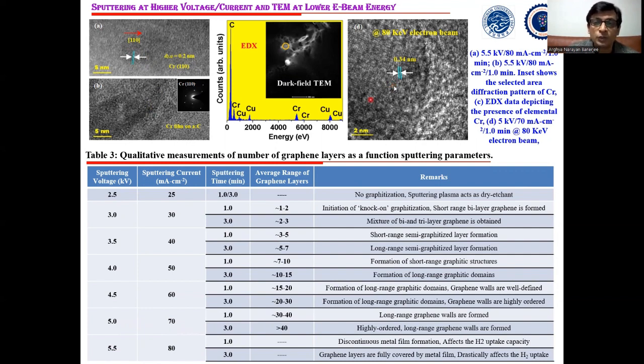And one more thing which we actually corroborated: generally, when we put this amorphous carbon film inside a high resolution TEM system, because a high energy electron beam is irradiated on this amorphous film, this electron beam sometimes can create this graphitic network. So therefore, to prove that this graphene network is not because of this high energy electron beam, but because of the sputtered particles, we actually did the TEM imaging at a very low electron beam energy, 80 keV instead of 200 keV, and we were still able to observe this graphene network. So this is clearly corroborating our observation that these graphitic microporous carbon networks are fabricated through the sputtering technique.